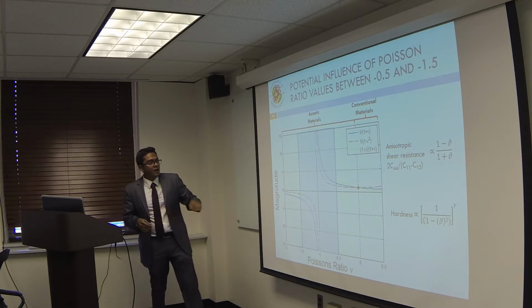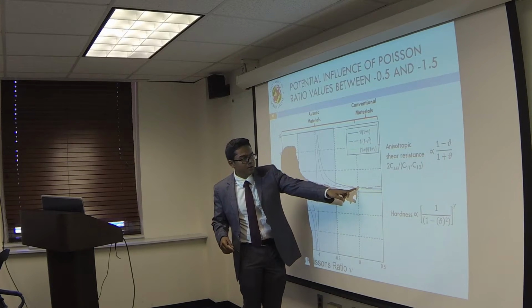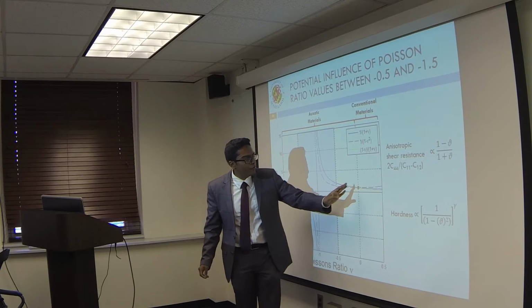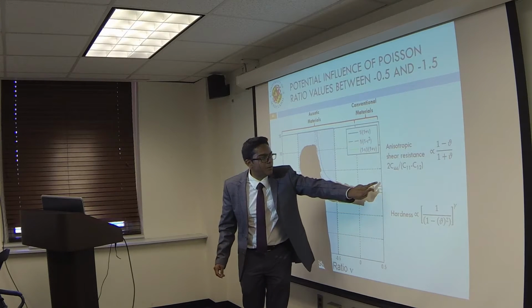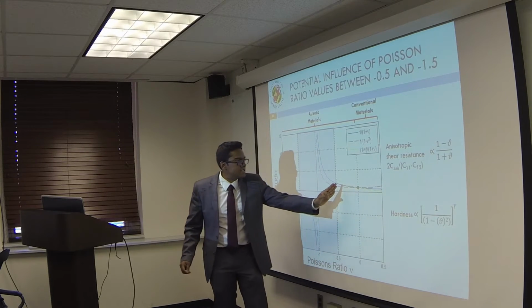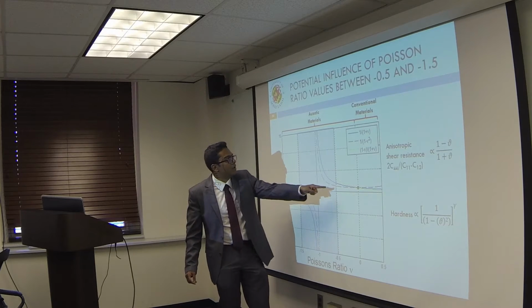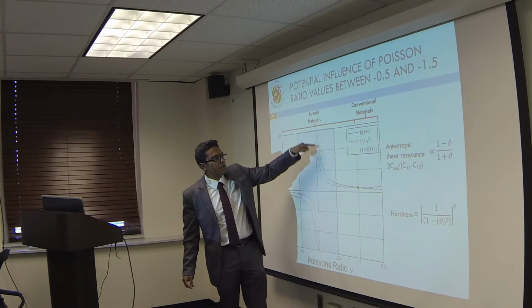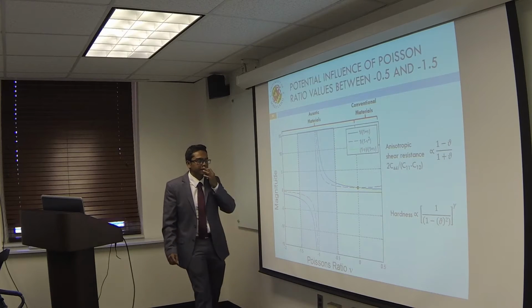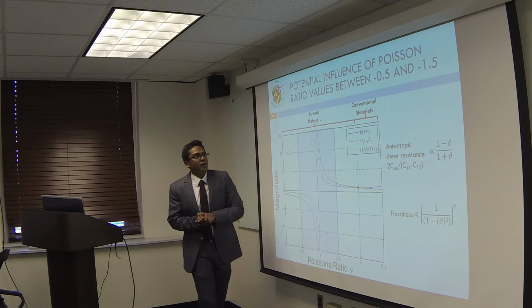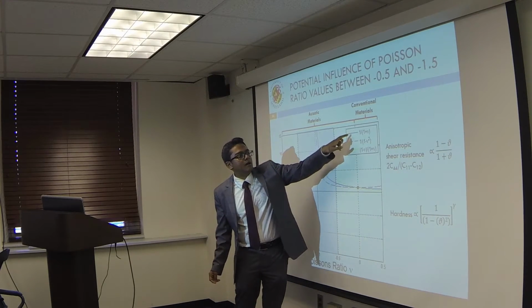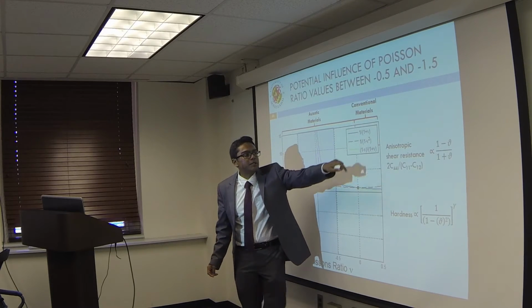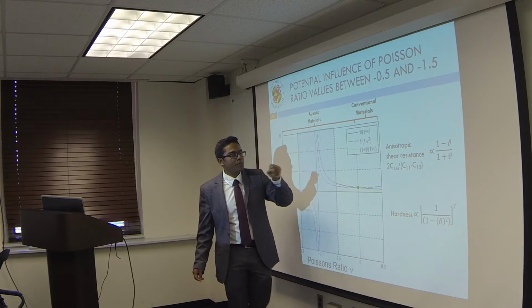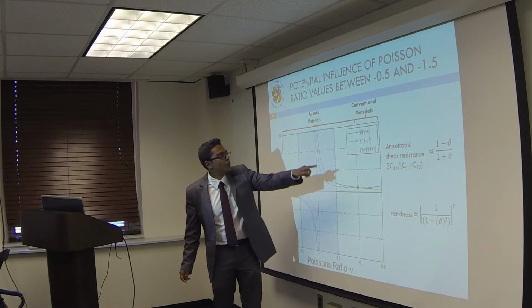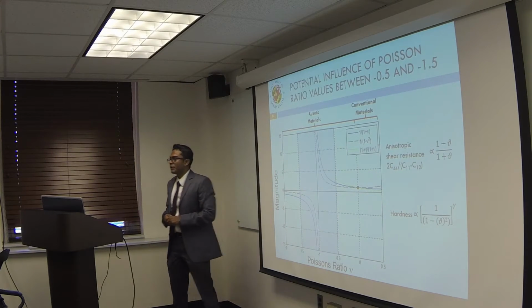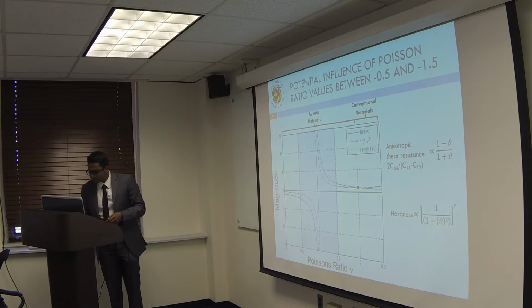you can see that at 0 Poisson's ratio, you're right here on the curve. And for a small increase in the Poisson's ratio, you get a small increase in these mechanical properties. But as these values tend closer and closer to -1, you get really large increases in the magnitude of shear resistance and hardness. So for isotropic materials, the shear resistance varies as 1 over (1 plus nu). And since we have an anisotropic system, it's (1 minus nu) over (1 plus nu), which is a sharper increase in the value of mechanical properties.